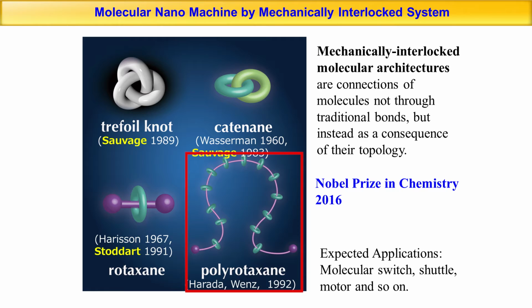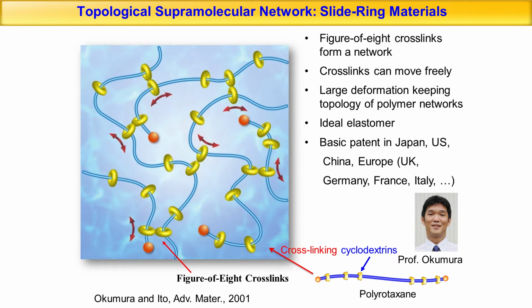Polyrotaxane is like a necklace with many rings. And this polyrotaxane was introduced in 1992 by Dr. Harada. In our research, we decided to cross-link these rings of polyrotaxane. What's unique about this is that, unlike typical cross-linking, we don't directly connect the strings. Instead, we first use these rings to thread through and then connect those rings together. We cross-linked them, as we did in 2002.